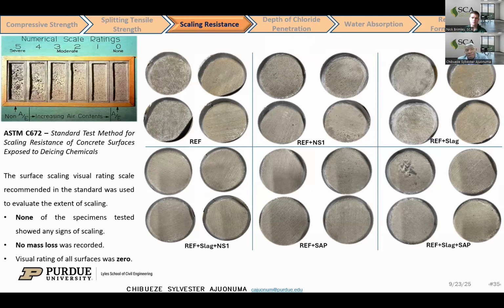So for all the specimens that we evaluated, none of them showed any sign of scaling. There was no mass loss recorded for the 50 cycles, showing that there was an improved performance of the concrete structures, which have a strong resistance to scaling.